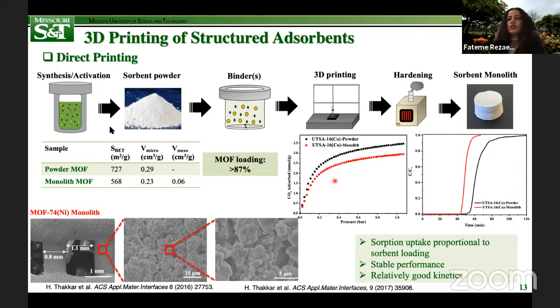As you can see, the adsorption capacity for MOF monoliths prepared by direct printing is comparable to that of parent material. I should also mention that some of the disadvantages of this technique include long preparation time as well as some degree of crystal decomposition during formulation process. This is something that we observed while formulating some MOF materials. There's also a slight chance of penetration of binder and printing solvents into the pores, which reduces the accessibility to active sites in the adsorbent pores.